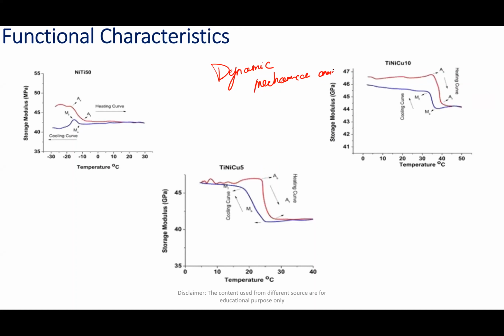So considering the elastic energy storing properties of the material, the properties were analyzed on cooling and heating measurement by using several frequencies of applied dynamic force. Basically the structure will look something like this. If this is our sample, we mount it and apply a dynamic loading on this structure, and we also study the austenite. From this we can estimate the austenite phase, the austenite start and finish, as well as the martensite start and finish of the structure. This is not similar to what we call Young's modulus. This is almost away from the DSC.